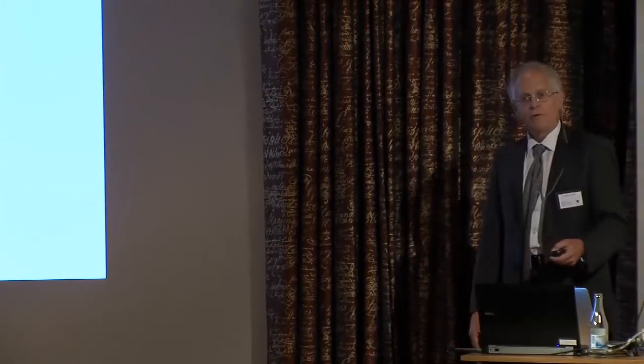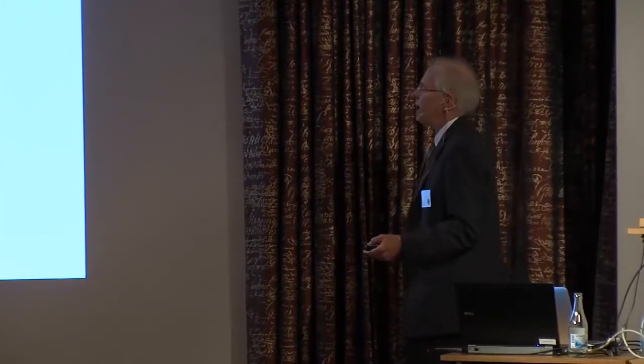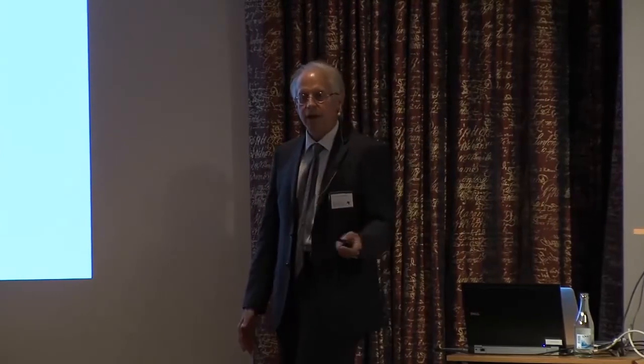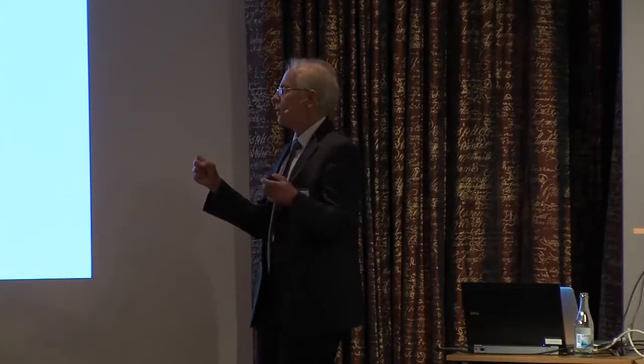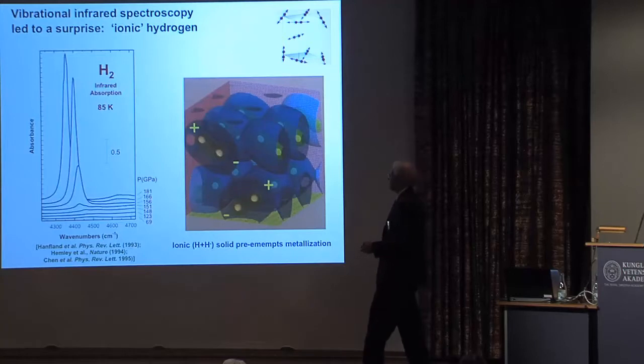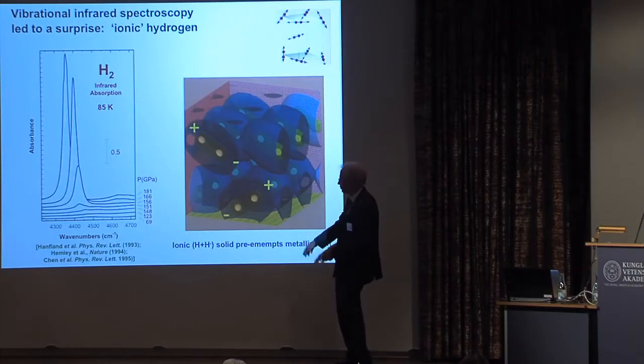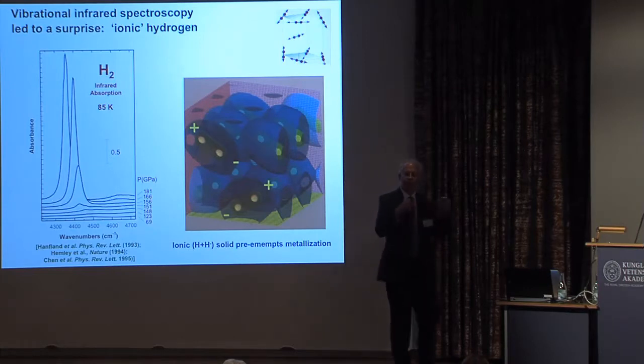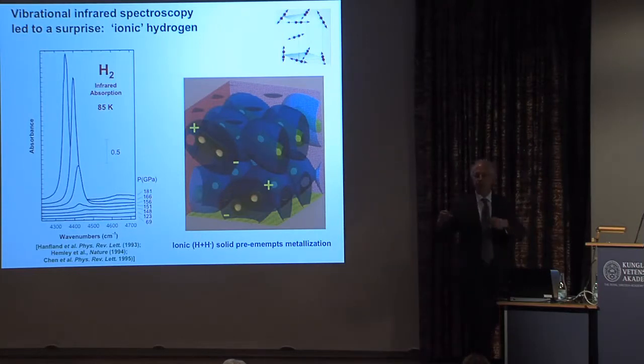Well, vibrational spectroscopy actually led to a major surprise here. Instead of becoming a metal, it becomes an ionic material. That is a type of charge transfer salt. There's a symmetry breaking, a polarization that develops across the molecules. Instead of the electrons going into the conduction band, you get this symmetry breaking, and this preempts the metallization.